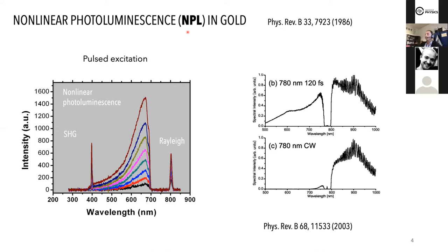So NPL was first reported in 1986, so almost 40 years ago. It was basically forgotten until 2003, when I was with Mike and Lucas starting to look at this. Basically, if you take a piece of gold and you shine a pulsed laser on it, because it's a nonlinear signal at the end of the day, as you will understand a little more later, you need the high peak power of pulsed excitation. So in the remainder of my talk, I will be mostly focusing on femtosecond laser chains, okay?